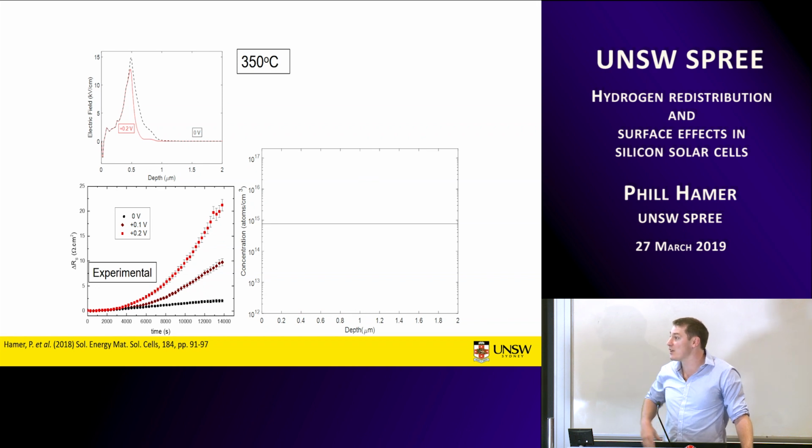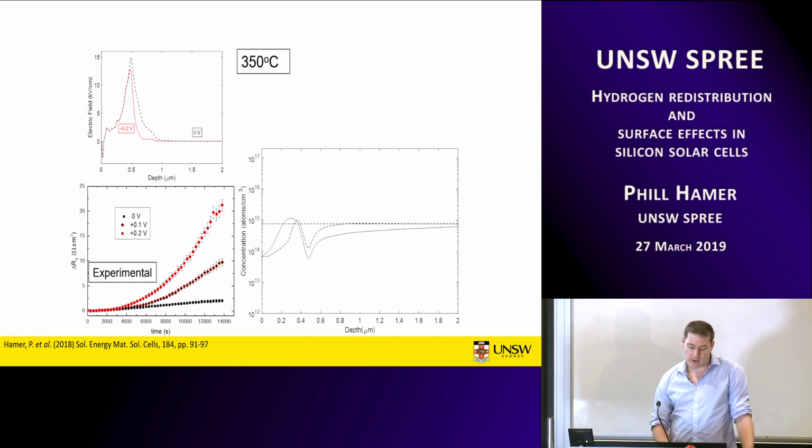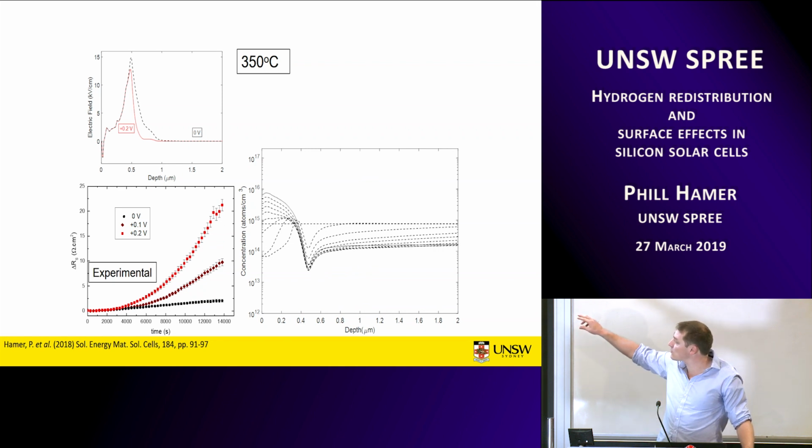This is where the hydrogen is in the positive charge state and where an electric field would repel it away from the surface. As a result of that electric field in that region being decreased, we can see a much smaller dip from the bulk concentration down to our crossover point. And this allows far greater redistribution of hydrogen to the front surface,